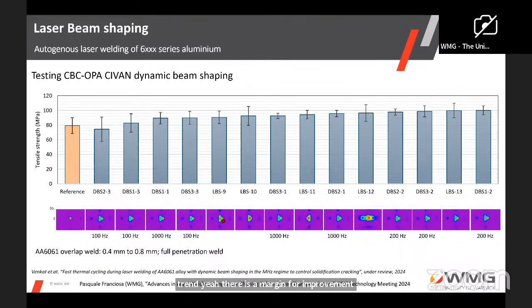So this only suggests one thing in the end, that changing the shape from a round, axially symmetric Gaussian or close to Gaussian profile to something else, like a triangular profile, has two main benefits. First, the possibility of changing the thermal gradient, especially in the lateral direction. And then by reducing the thermal gradient, eventually you are reducing thermal stresses, and because of the impact during solidification on the grain structure, there is a better chance that the welds will sustain the thermal load and wouldn't crack in the end.